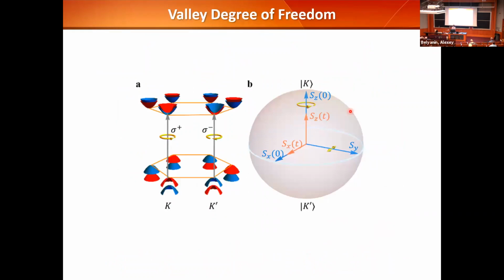And then another thing that's unique is these excitons that we see in the light emission spectrum. They actually happen at the corner of the Brillouin zone. And there are two copies, which we call the K and K prime valley. At the K valley, the color scheme here represents spin state. And a photon carries angular momentum of 1. So you need a certain spin state in the valence band and conduction band to make an allowed optical transition. It turns out in one valley, you can make that allowed optical transition with circular plus light. And in the other valley, you have to access it using an opposite helicity photon.